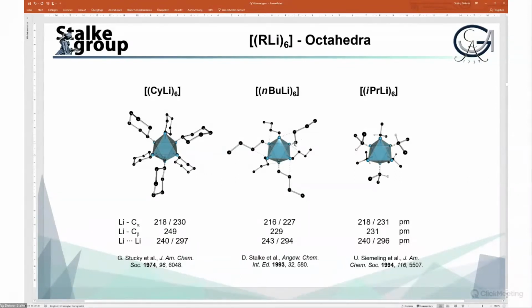So the contact to the C-beta was envisaged to be a sort of agostic interaction from the lithium to the hydrogen atoms of that carbon, but that was cleared up later in 2001 by our dear colleague Wolfgang Scherer. There was no bonding interaction between the lithium and the hydrogens. There is an interaction between the carbon and the lithium. The carbon has the most charge density, and that is attractive to the lithium.